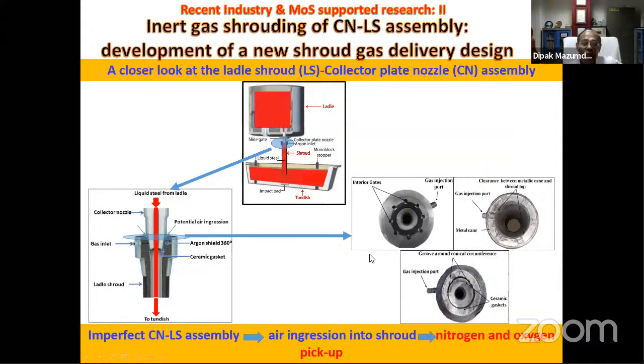Now we are looking globally at the tundish. Now let us look locally in the tundish, at the shroud and collector nozzle joint, which I have highlighted here. Let us look at what happens here. So this is the joint between 2 refractories here. And this is the ladle shroud, which is mounted onto the collector nozzle. And you can mount it with a robotic arm, or you can have some kind of a manipulator, who can force fit the shroud into the collector plate nozzle and inject.